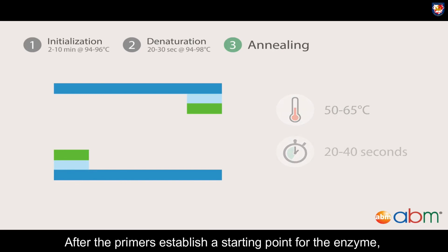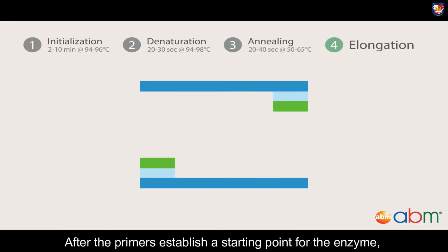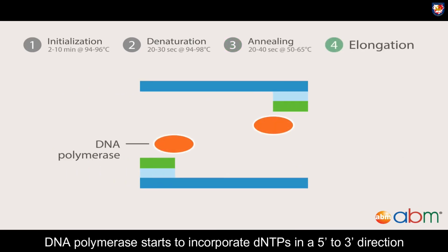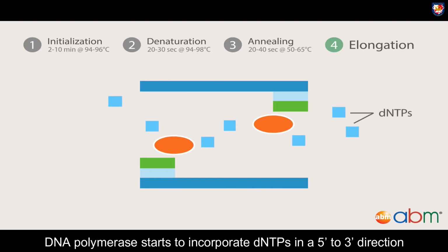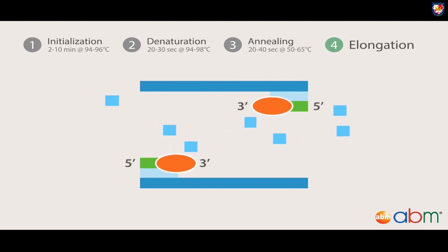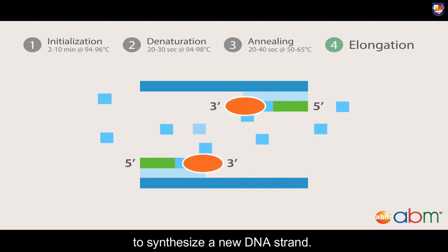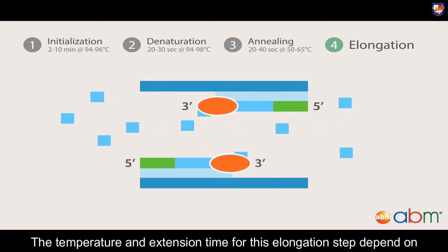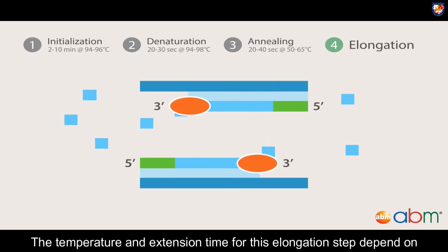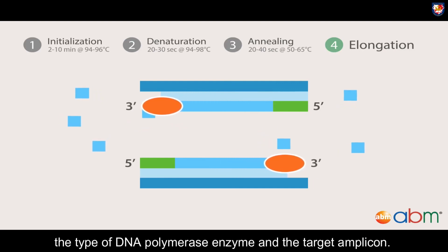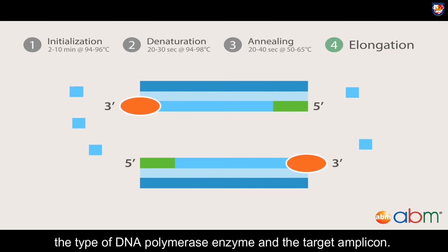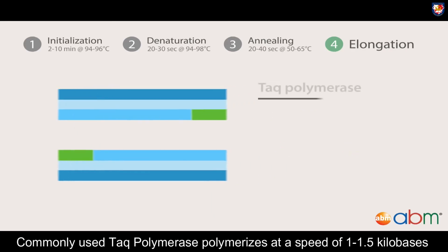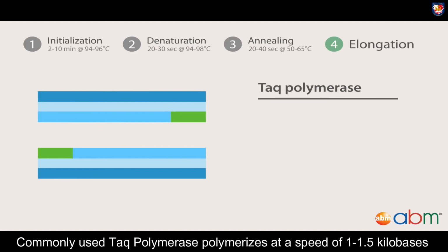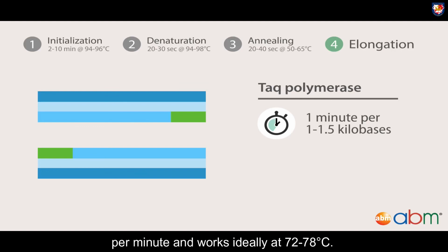After the primers establish a starting point for the enzyme, DNA polymerase starts to incorporate dNTPs in a 5 to 3 direction to synthesize a new DNA strand. The temperature and extension time for this elongation step depend on the type of DNA polymerase enzyme and the target amplicon. Commonly used Taq polymerase polymerizes at a speed of 1 to 1.5 kilobases per minute and works ideally at 72 to 78 degrees Celsius.